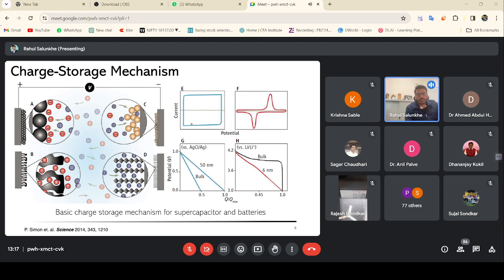In this case of electrical double layer capacitors, for charging and discharging we can get a very rectangular shape. No redox peaks can be observed, because mostly the electrical double layer is formed on the surface. There is no redox reaction occurring in the material. So the charge comes, gets adsorbed on the surface of the material and gets desorbed. And because of that, a very rectangular CV shape we can obtain in the case of electric double layer capacitors.